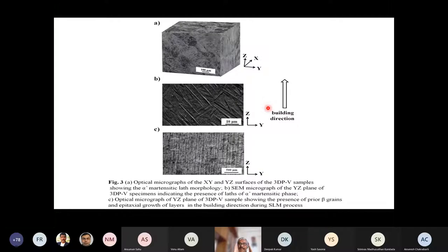And why heat treatment is important, because normally by additive manufacturing we go to a near net shape product. So our turbine blade is exactly of the shape of a turbine blade. We have no further choice to make any plastic deformation or any change or any machining unless we really take into account machining allowances and all that. So we don't have to do it. But heating and cooling we can always control. So just by a heating and cooling cycle, if we are able to improve the performance, that is one big step in this area, which we have done.